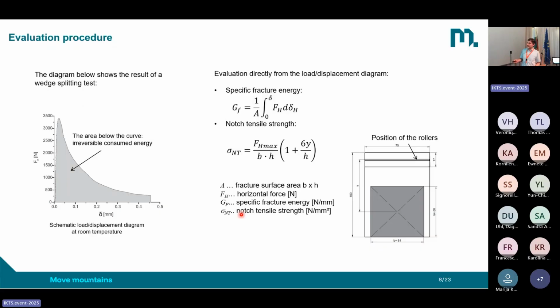How can we then evaluate the test? We see here a load displacement diagram, again with maximum force and then with the softening behavior. And we have this area under the load displacement curve, which represents the energy consumed for the fracture process. How is it then calculated? Specific fracture energy G_F is 1 over A, so this is the cross section of the fracture surface, multiplied with the integral over the load displacement curve. So we integrate the force F_H and multiply it here with the displacement.